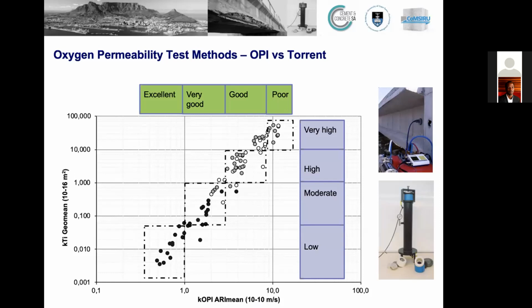And we compared the South African design approaches to the Swiss design approaches where this method is being used. And for example, one way to do this is to characterize the concrete. And in our case, we say we have very high permeability, moderate, and low permeability. And in Switzerland, they talk about poor concrete quality, good, very good, and excellent concrete quality. And we tested dozens of concrete mixes to find out that in nearly all cases, we would place the concrete in the same category of quality, which of course confirms that both these methods have similar merits in identifying the quality of the concrete, which is quite encouraging.